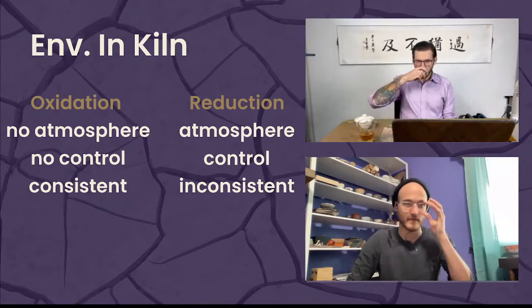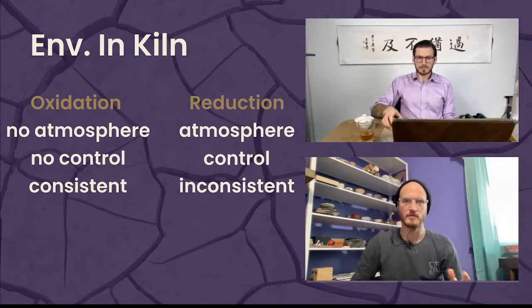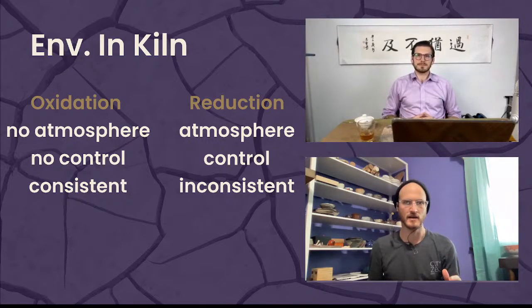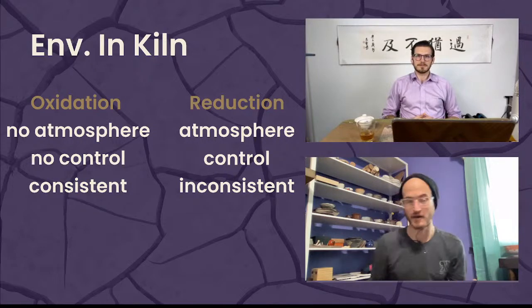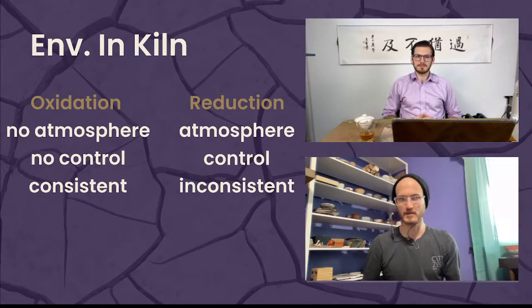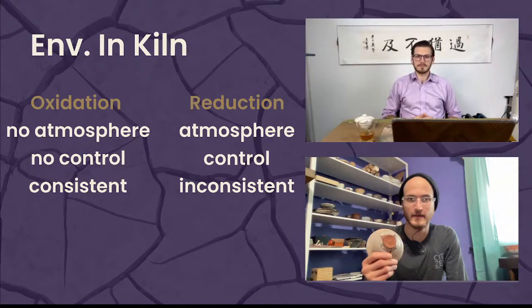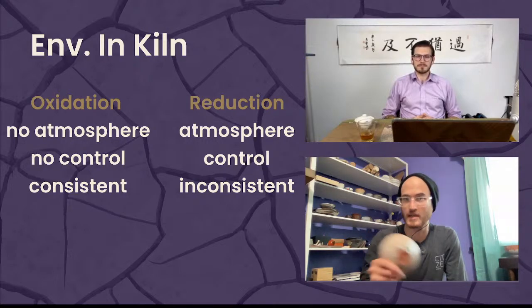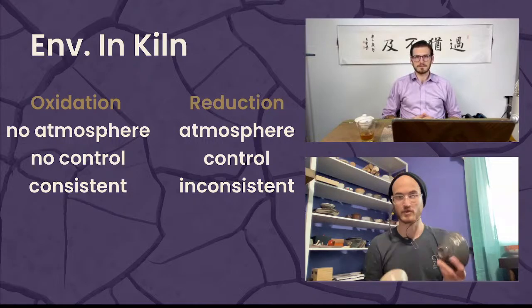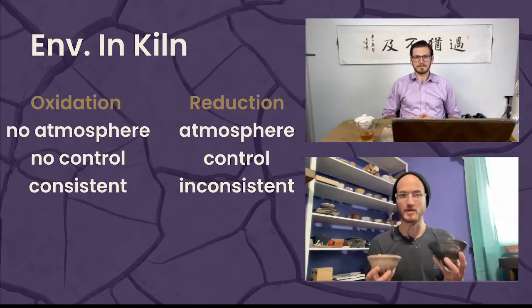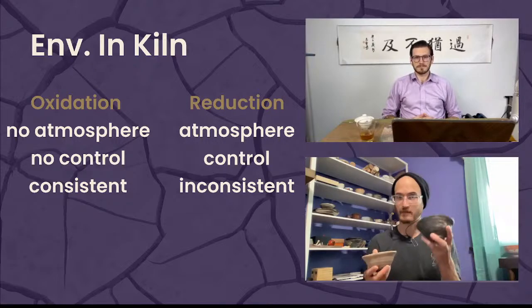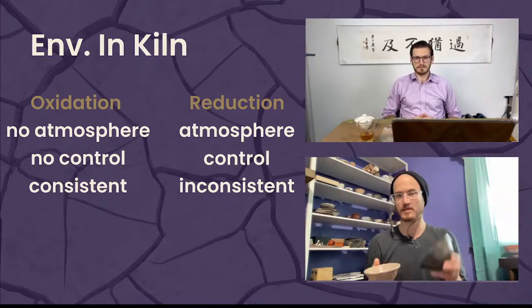Yeah, and the reason why we want to fire in reduction kilns, in gas kilns, in a wood kiln, in a coal kiln, which is less common now, is just because you have that control. In an oxidation kiln, in an electric kiln, you always are going to end up with the same result, which is desirable because you know it's going to be the same every time. There's really no change in conditions. But with a gas kiln, right, you have to control every aspect of the firing and make sure that whatever you're doing is influencing the clay and the glaze in the way that you want it to.